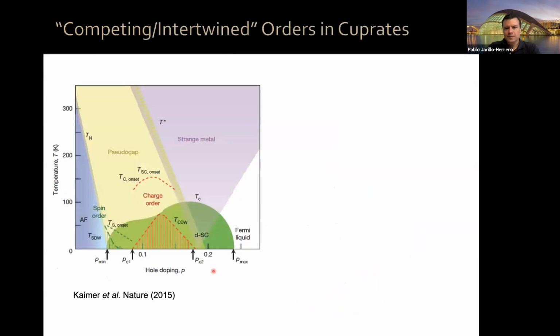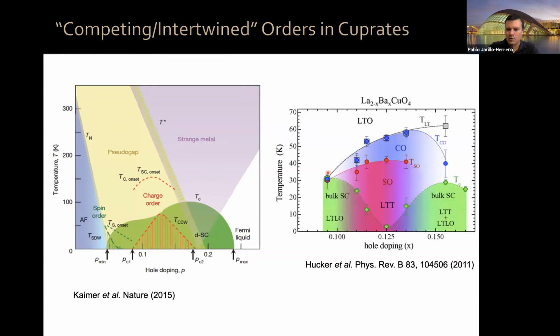Okay, so what does the term competing, or sometimes intertwined, orders mean? This has been mostly explored in many correlated materials, but explored perhaps more in depth in the cuprates. Here you have the phase diagram, temperature versus doping, for high temperature cuprate superconductors. And as you can see, the superconducting dome here is not just a single dome. It has sort of two domes. There is a depletion here, okay? Now, in some cuprates, the depletion goes all the way, it makes Tc go almost all the way to zero, like in here, like in lanthanum barium copper oxide, okay?